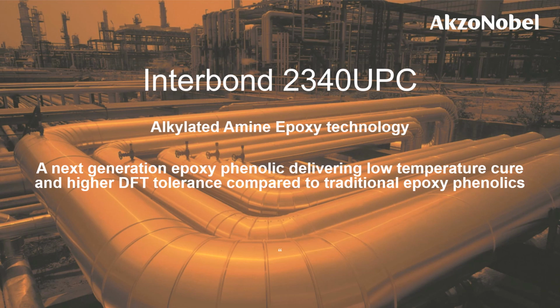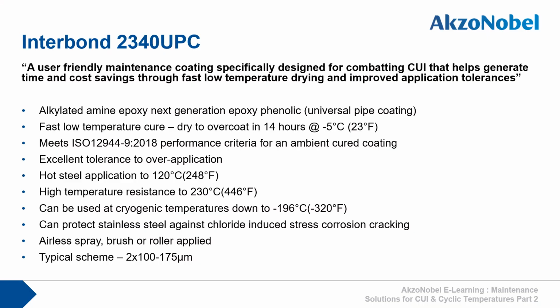Interbond 2340 UPC, where UPC stands for Universal Pipe Coating, is an alkylated amine epoxy technology, which is a next-generation epoxy phenolic, delivering low temperature cure and higher DFT tolerance compared to traditional epoxy phenolics. Interbond 2340 UPC is a user-friendly maintenance coating specifically designed for combating CUI that helps generate time and cost savings through fast, low-temperature drying and improved application tolerances.